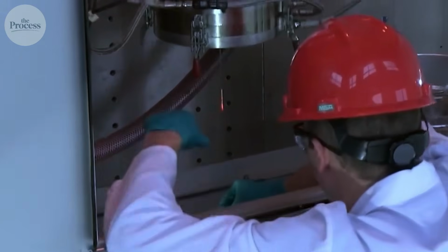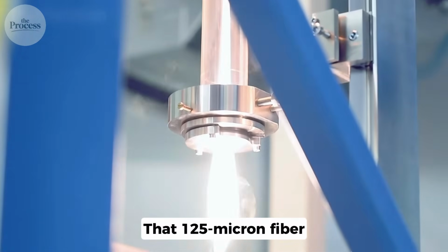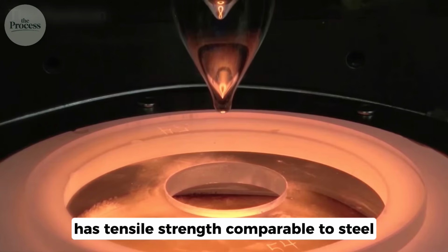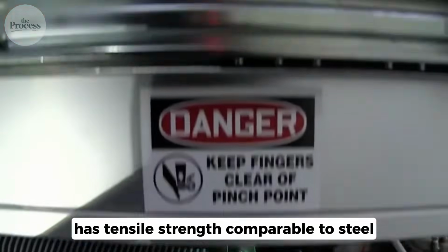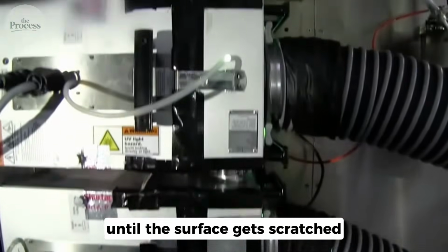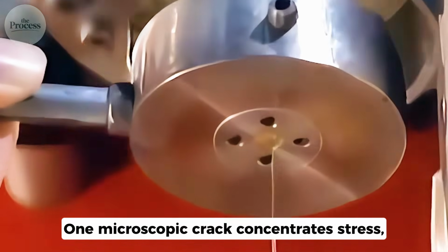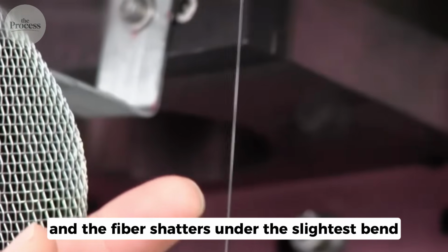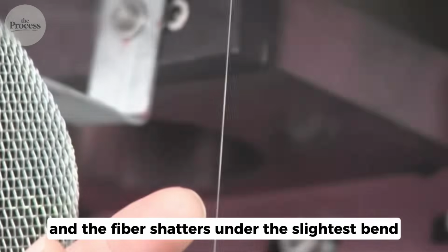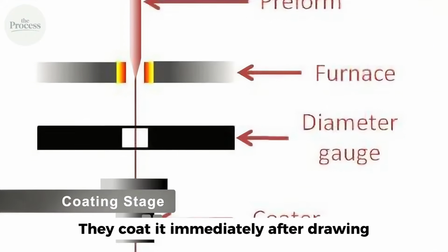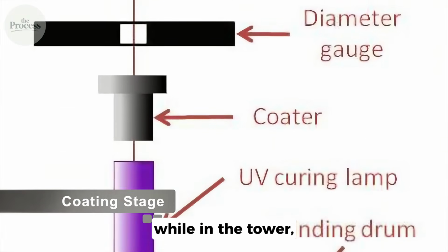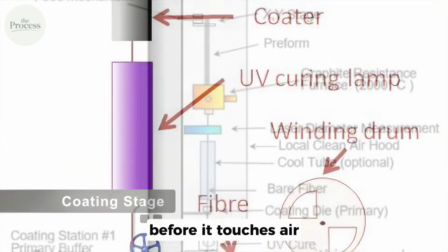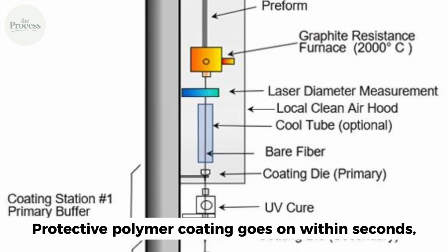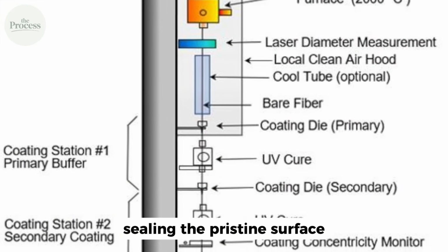You've watched technicians handle fiber cable like spider webs, wondered why they're so paranoid. That 125-micron fiber has tensile strength comparable to steel until the surface gets scratched. One microscopic crack concentrates stress, and the fiber shatters under the slightest bend. This is why they coat it immediately after drawing, while in the tower, before it touches air. Protective polymer coating goes on within seconds, sealing the pristine surface.